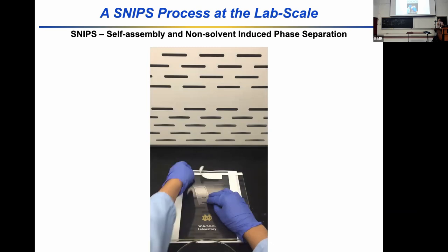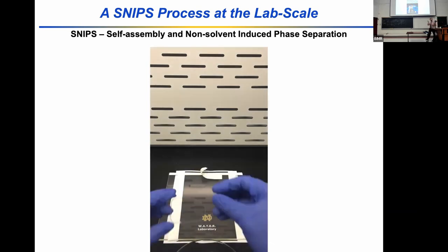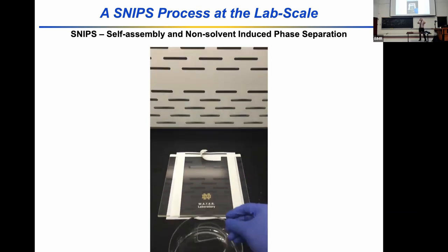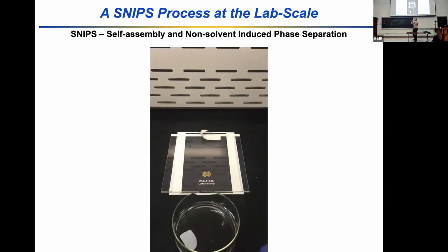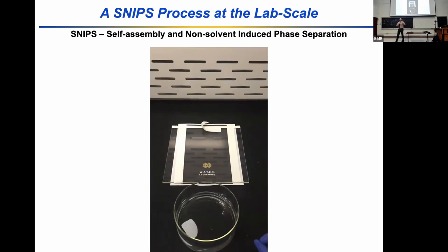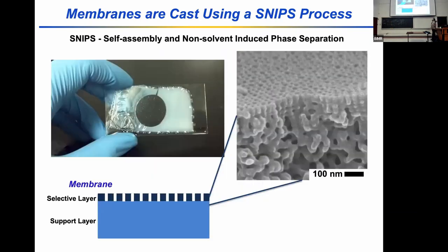There's an evaporation step, and the evaporation step is critical in the approach that we're using because it increases the polymer concentration right at the solution-air interface, driving that self-assembly. And then we just plunge it into a non-solvent bath to kinetically trap the polymer structure in place. And when that's done correctly, we've had a lot of success creating asymmetric membranes with a thin self-assembled active layer. So that membrane that gets pulled out of the bath that you saw in the last video, we can punch 1 inch diameter circles out and put them into our test cells.